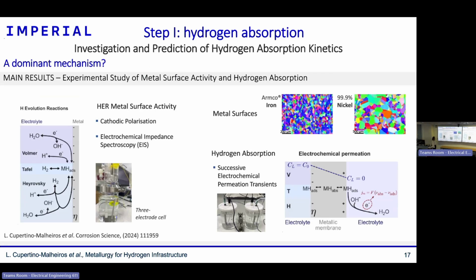All right, so I have done a series of electrochemical tests in the lab. Part of those tests are related to the activity of the metal surface, so how much hydrogen gets produced. But in those tests, we are not measuring the hydrogen that has been absorbed. Another part of the experiments uses an approach called electrochemical permeation, in which there are two electrochemical cells. One cell again has hydrogen produced at the metal surface, but now we can detect on the other side the hydrogen that got absorbed at the membrane. In this case, I use two model materials, pure iron and nickel.